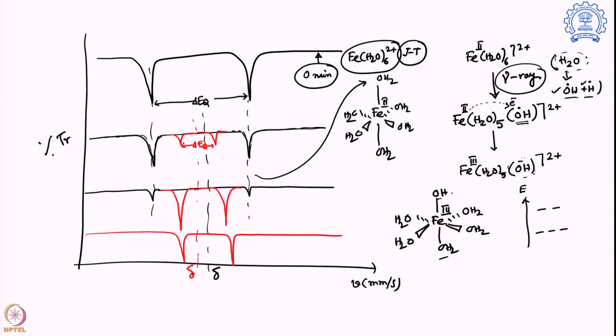Now H2O and OH minus are all sigma donating, pi donating ligands. So over here it is going to be a high spin system, iron 3 plus is a d5 system, so all the 5 electrons will be stored like this. Now you can see all of them are symmetrically oriented, so there will be no valence contribution to the electric field gradient. So it will be 0 for the valence, but for the lattice one, you can see it is asymmetric because 5 of them are water, 1 of them is hydroxide. So lattice EFG will be there, non-zero.